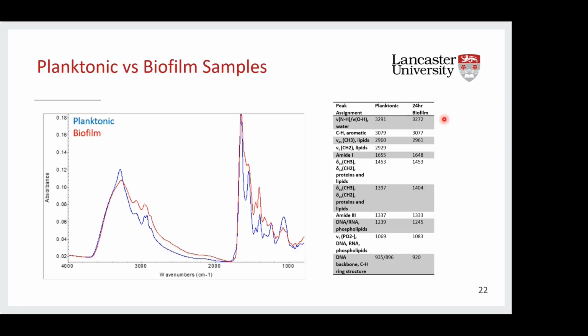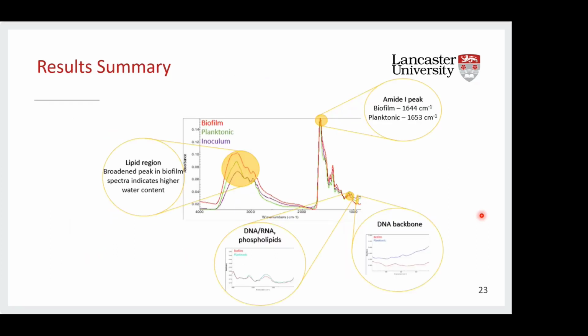From tabulating all of our data like this, we can infer two key things. Firstly, you have a change in peak position, or the wave number, and this relates to slightly differing chemical structures that cause that signal. Then you also have increasing and decreasing absorptions. If you have, for instance, this peak at the same wave number, the increased absorption indicates that you have a different abundance of that same chemical component. Through the work that we've done so far, we have spectroscopically differentiated between biofilm samples and planktonic samples that have been formed from the colony used to make that biofilm.